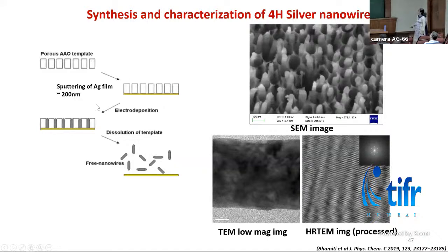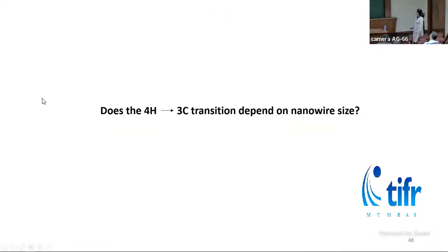These porous silver nanowires were synthesized in a porous anodic alumina template, and after dissolving that template, we could get free silver nanowires. This is the low mag TEM image of the sample, and the high mag TEM image shows that these wires are nicely crystalline and defect-free nanowires. Now the question we asked here was, does the 4H to 3C transition depend on nanowire size?